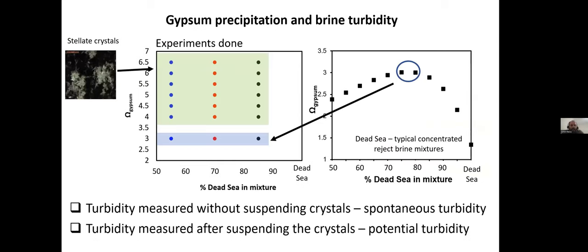So I did multiple experiments under different conditions. I did a set of conditions experiments. You see here in the greenish background, mixing ratios of 85, 70, and 55% Dead Sea. These correlate to the maximum oversaturation, maximum precipitation potential, and a similar oversaturation to the current Dead Sea with different mixtures. And I did a set of experiments in the conditions where we saw earlier spherulitic experiments, because I've seen these in suspension in the previous experiments. I also did a set of experiments at an oversaturation of 3.